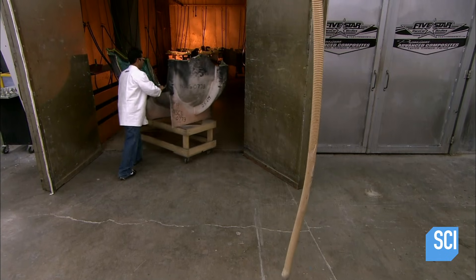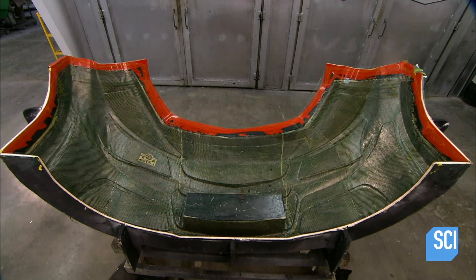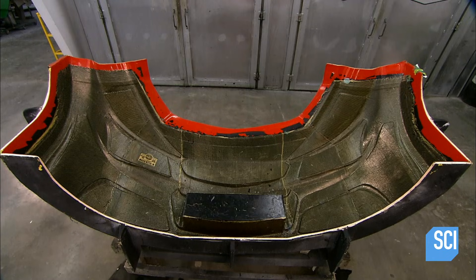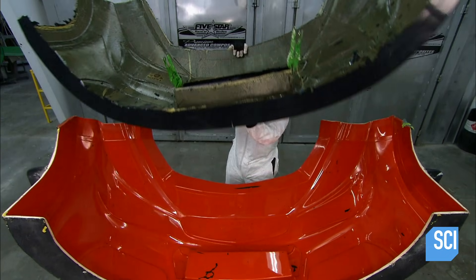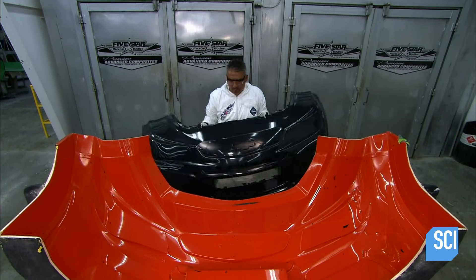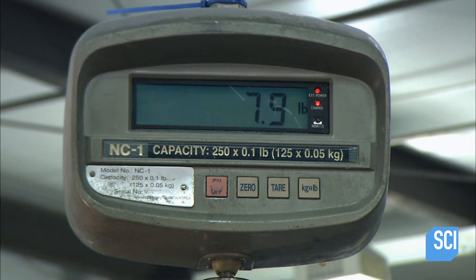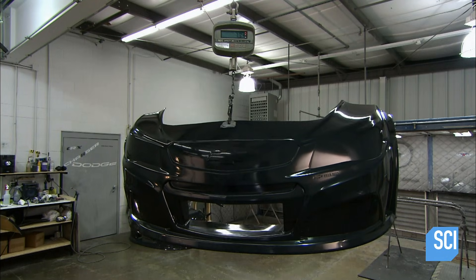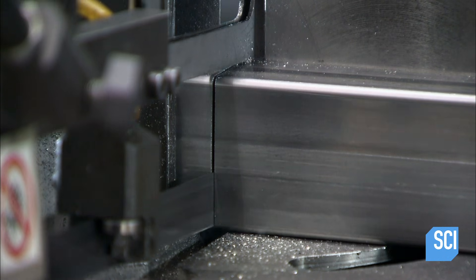This both smooths and compacts the carbon fiber layers. Then it's into a hot oven to bake for three hours, which activates the epoxy and combines the layers of carbon fiber and Kevlar fabric. An employee removes the completed stock car panel and inspects it, then it's over to a weigh station — at just under eight pounds, the part is lightweight yet virtually shatterproof.